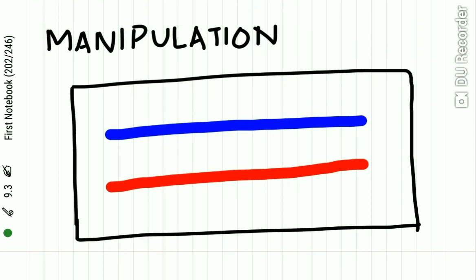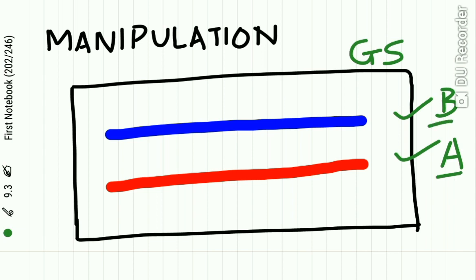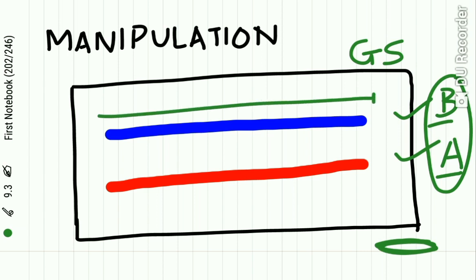Now, let us see how to manipulate this zinc oxide eugenol impression paste. On a glass slab, you squeeze out equal length of ropes of each of the base paste and the accelerator paste. Now, how can you control the quantity of this paste? They should be equal. So, the orifices of the tube or the openings of the tubes should be of equal diameter, and the equal length of the two pastes are taken on the glass slab.